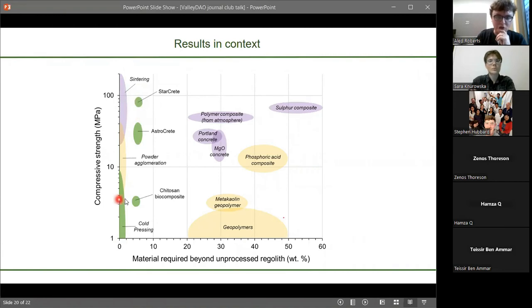And the colours represent energy use. Green is low energy processes, yellow is medium energy processes, and purple are high energy processes. And obviously you don't want to use too much energy, for reasons mentioned before. So ours is a relatively low energy process. There's no high temperature sintering or anything. So we occupy a nice sweet spot up here.